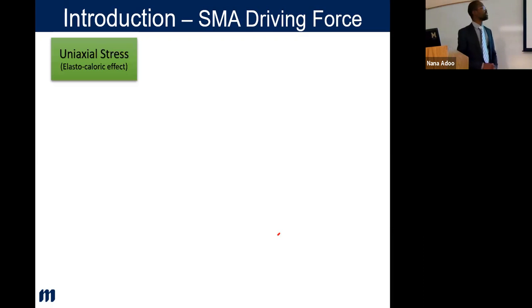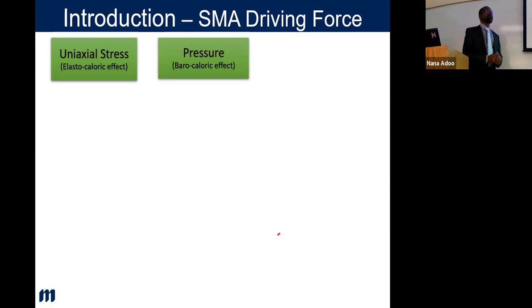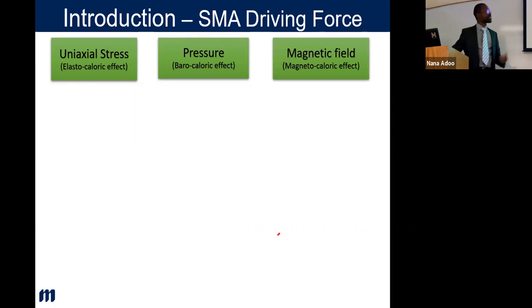So based on the kind of force field you are using to drive that shape memory or shape recovery process, you could have it in a uniaxial form, or compressive stresses. This we call the elastocaloric effect, because of the heating that is coupled to it. If it's pressure, it is the barocaloric effect, and then a magnetic field, of course, will be the magnetocaloric effect as a result of this heating.